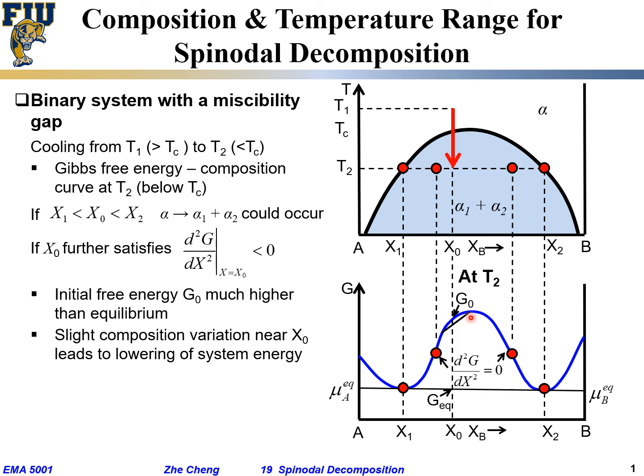In the beginning of this fluctuation, the interface between the leaner portion and the richer portion cannot really be seen or distinguished, because the lattice parameter difference is very very small. This is very different from, say, silver coming out of copper, where the lattice parameter difference is too large and the two phases don't try to fit together at all. This process is what people call spinodal decomposition — going from one phase to two phases.